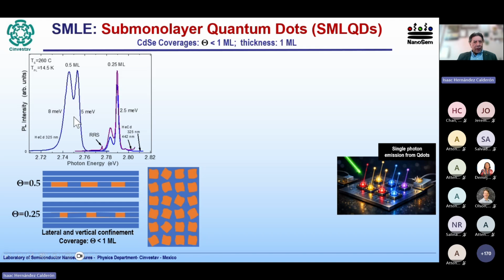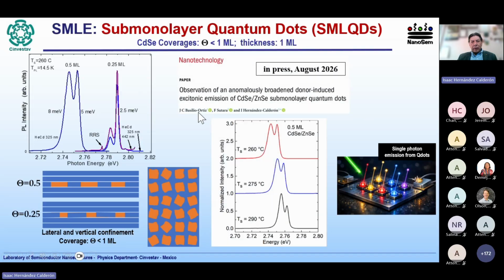This two-peak structure has been the topic of debate for many years because the low energy peak presents a broader width than the higher energy peak. This higher energy peak is due to localized excitons, and in principle, it could be expected that this would be thinner. However, since it's broad, many people have assigned this to structural defects. However, very recently, we have demonstrated that this broad peak, this low energy peak, is induced by donor impurities, that is n-type impurities, in the quantum layers. These quantum dots are very interesting for single photon emission in the case of new optical devices.